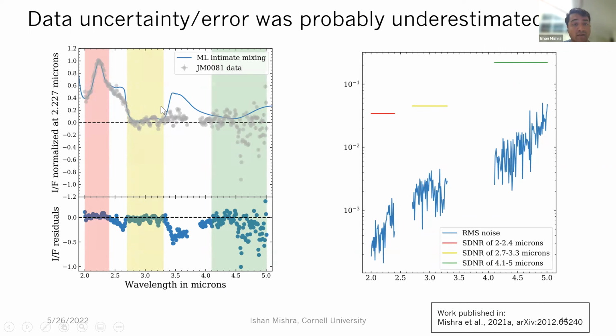Here I'm highlighting that, first, some of the wavelength regions were just not agreeing with our model. But even in the regions where the model was giving a good fit to the data, the scatter in the residuals, which is the standard deviation of the residuals in these regions, was much higher than the noise on the data. If everything is as expected, then the scatter in your residuals is on the order of the noise on your data. But this was off by an order of magnitude or more.